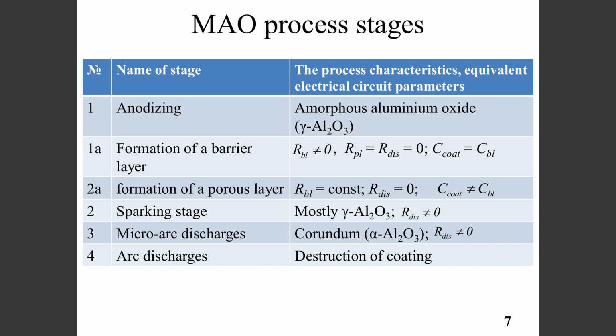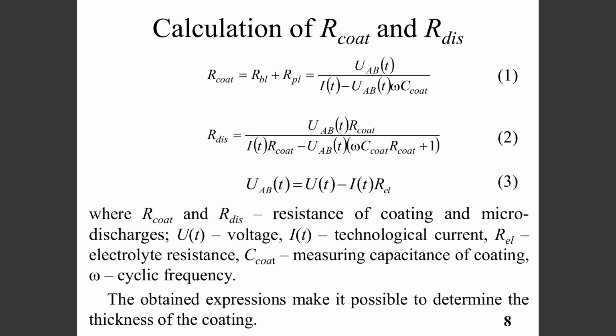With an increase in power of the microdischarges, a phase transition of amorphous alumina to a crystalline modification called corundum occurs. The higher the proportion of the corundum in the coating, the better are its mechanical, chemical and electrical characteristics. With an even greater increase in power of the microdischarges, the coating will be destroyed. During the study, expressions to determine the parameters of equivalent electrical circuit, such as resistance of the coating and microdischarges, were obtained by the use of Kirchhoff's law. This takes into account the possibility of measuring the current, voltage and capacitance of the coating and micro-arc oxidation process. The obtained expressions make it possible to determine the thickness of the coating and the power of microdischarges, respectively.